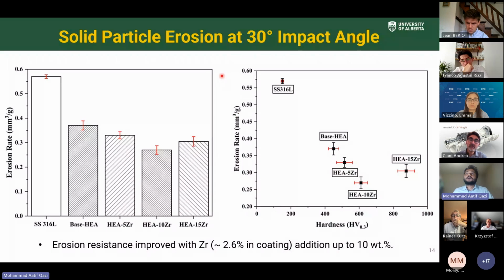The solid particle erosion testing done at 30-degree impact angle showed decreasing erosion rate up until Zr 10 weight percentage, and then a slight increase at 15 weight percentage. Comparing the erosion rate with the hardness, we see the erosion rate decreases with the increase in the hardness up until Zr 10 weight percentage, but then an increase in the erosion rate with the increase in hardness. So it shows that toughness also plays an important role in determining the erosion. Similar results were observed when solid particle erosion testing was done at 90-degree impact angle.